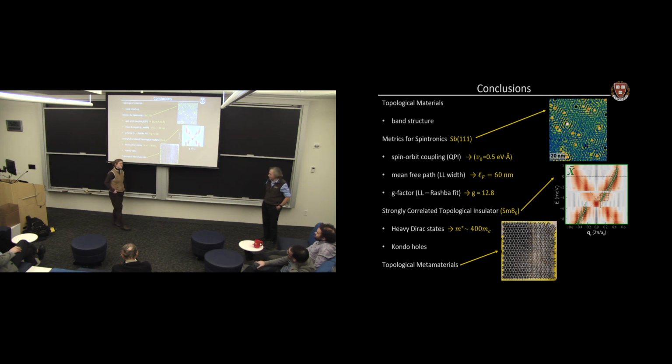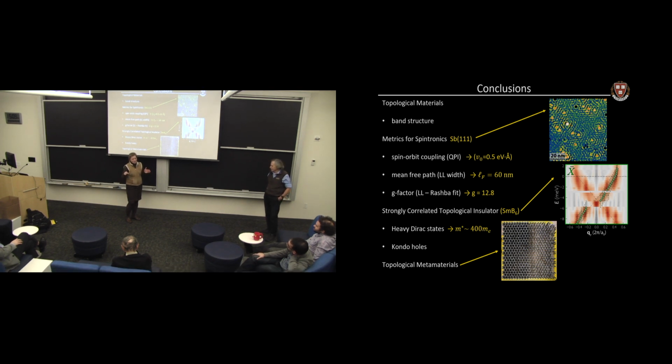Is there some feedback? Over 4 days, we typically do have a drift of a couple of angstroms, but we can correct that in software after the fact because we are simultaneously measuring the atomic lattice, and we know what the atomic lattice should be. It should be perfectly periodic. So we do a kind of a spatial lock-in amplifier technique.